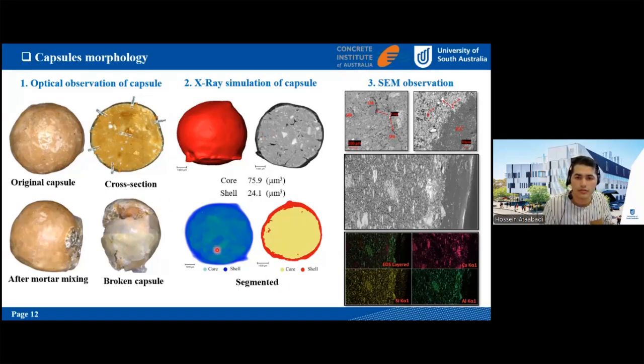Here is just an X-ray simulation. So we simulate the shell material and the core, so we could see if the core is totally covered, and it's proved that the shell material that we selected can cover the whole core very well.